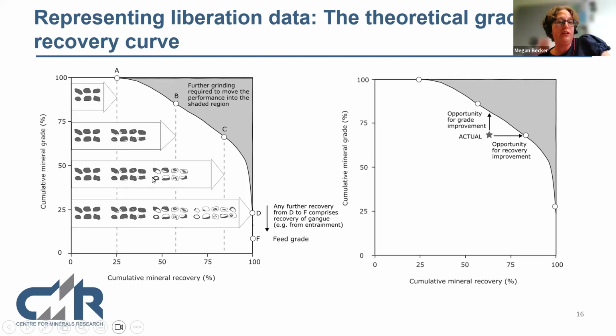We do this again with the low-grade middlings, and then the locked material. And so we then plot this curve. Obviously, once you've recovered all the valuable mineral, anything further that you would progressively recover would get you to F, which essentially is the feed grade.